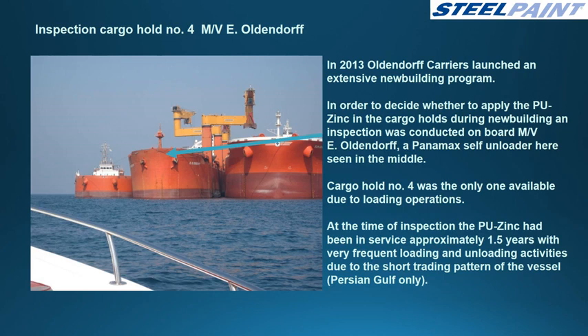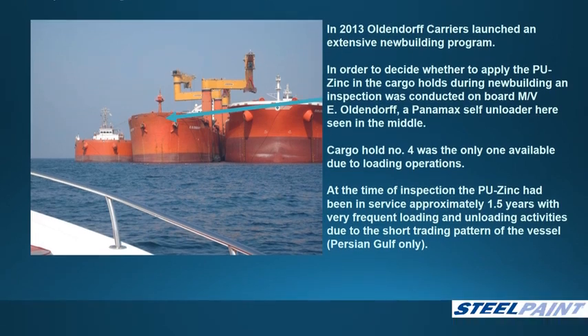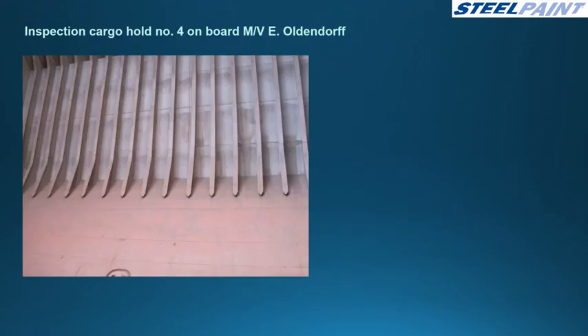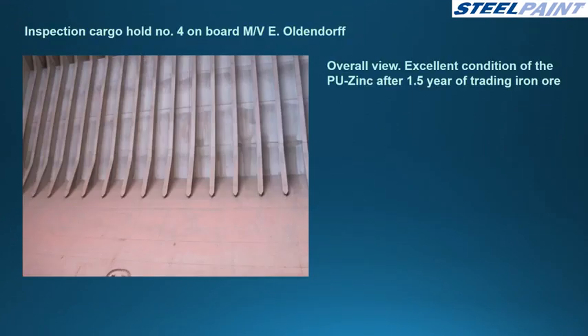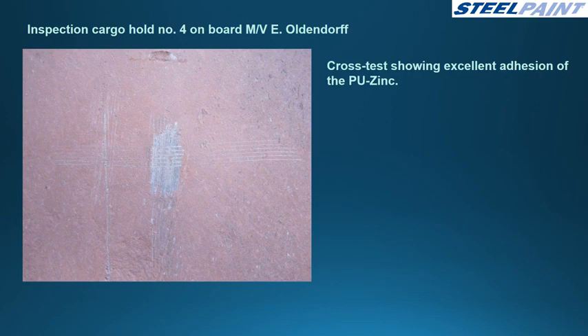At the time of the inspection, the PU Zinc had been in service approximately 1.5 years with frequent loading and unloading activities due to the short trading pattern of the vessel, Persian Gulf only. This is an overall view. Excellent condition of the PU Zinc after 1.5 years of trading iron ore. Here you see a cross test showing excellent adhesion of the PU Zinc.